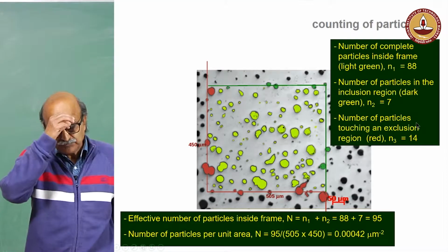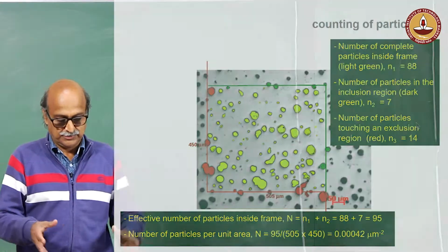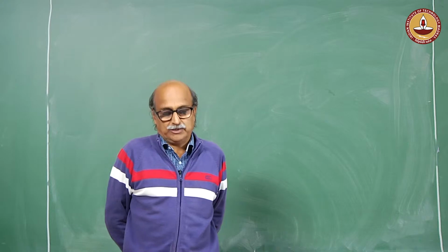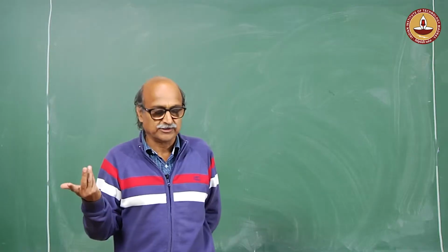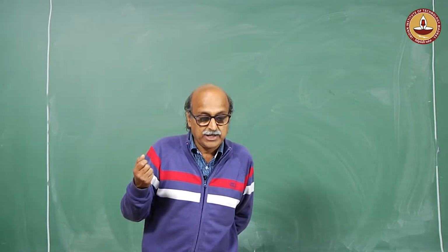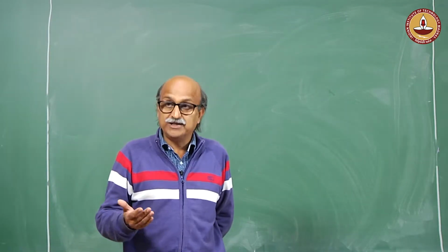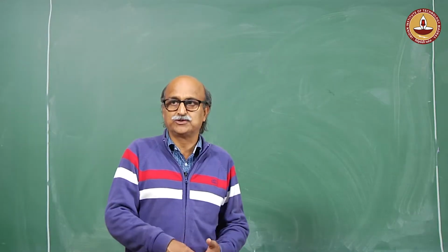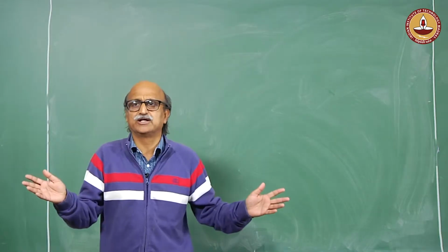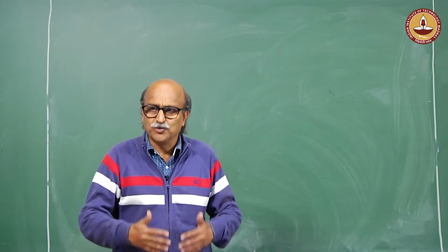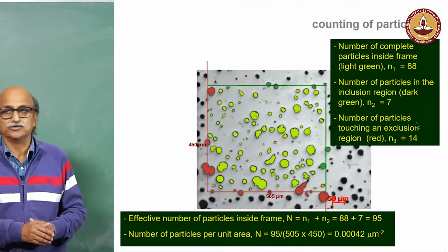Now, this particular idea of a count on a two-dimensional structure does not rely on what kind of shape of particles there are. Okay? Particle can be of any shape and you can still count them. This idea can be extended to 3 dimensions, and then you can do a count and get the actual numerical density N_V in a unit volume without knowing their mean tangent diameter, without knowing their shape. There can be particles of different shapes, you would be able to count those particles as well.